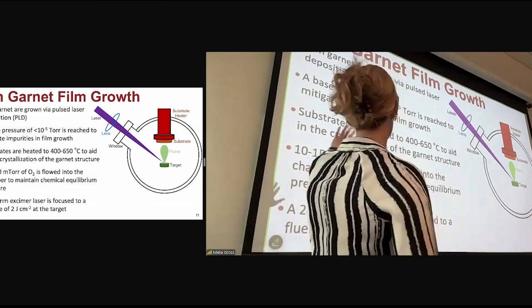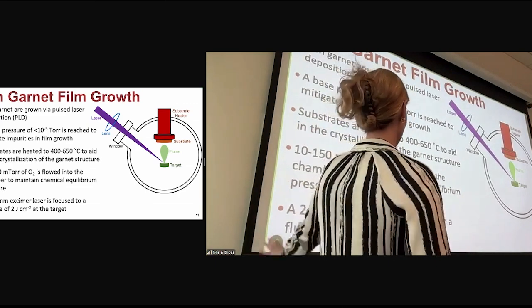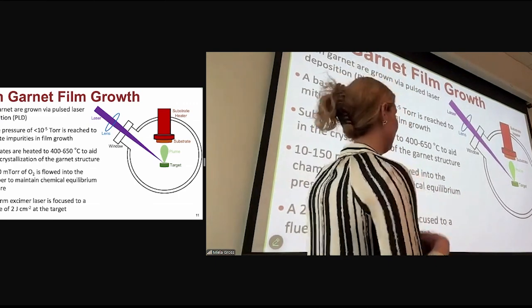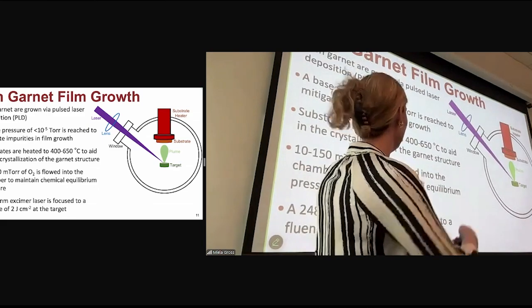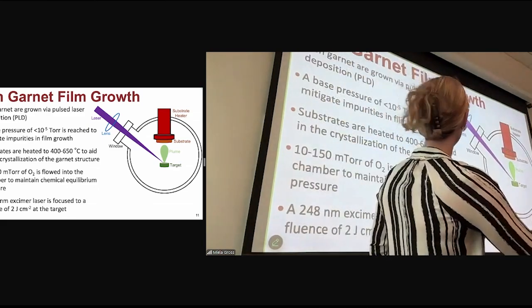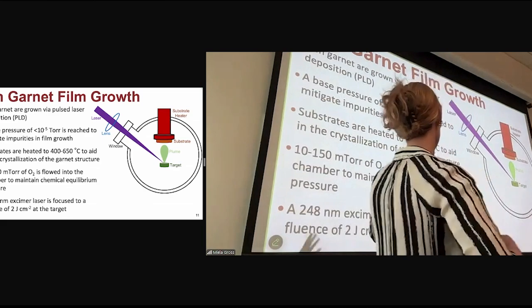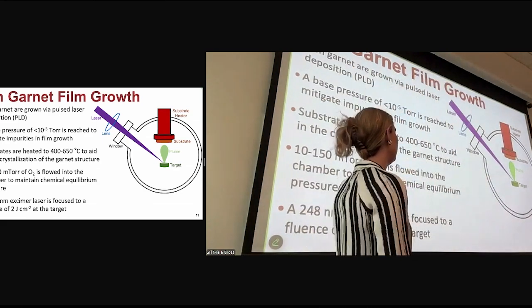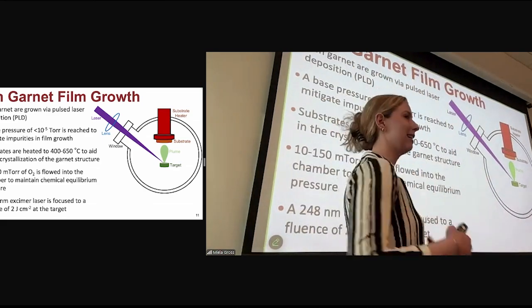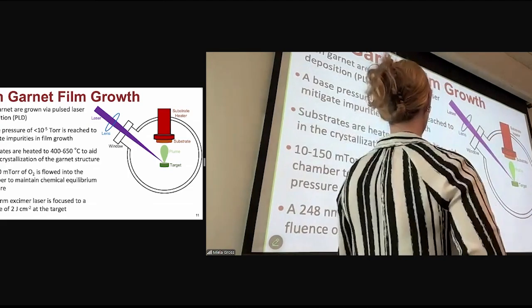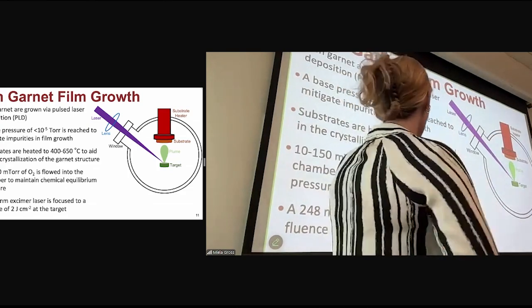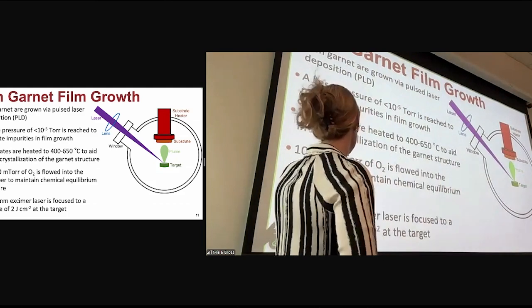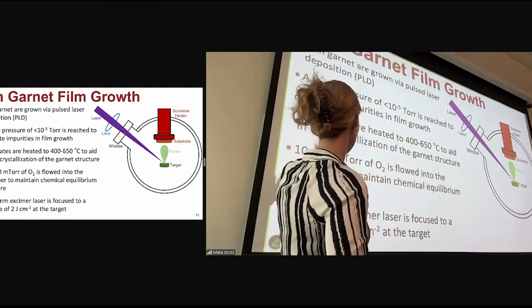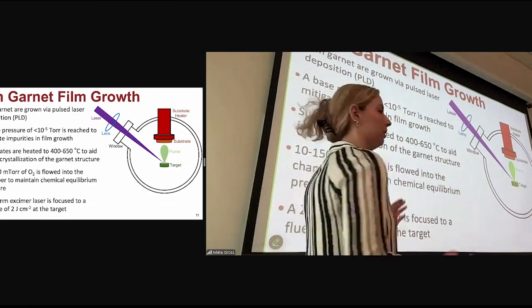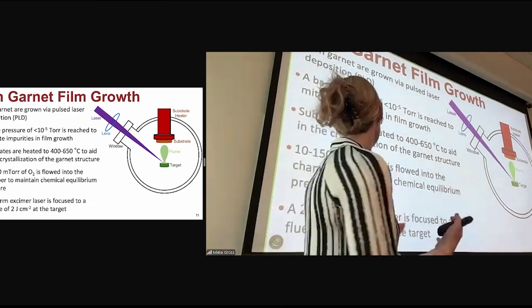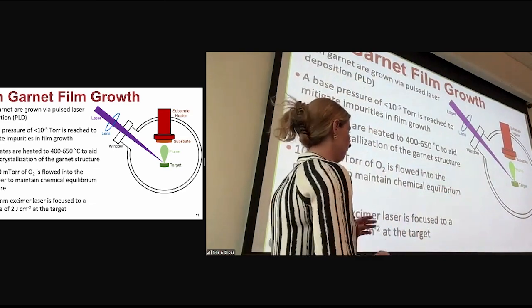So firstly, we can reach a base pressure of less than 10 to the minus 5 torr for our growths, and that mitigates impurities. Also, we have a substrate heater above our substrates, which allows us to heat the substrates to 400 to 650 C during our garnet growth. That adds extra kinetics to aid in the crystallization of the garnet structure. And we also are able to flow in oxygen while we grow these garnets, around 10 to 150 millitorr. And that actually helps us maintain chemical equilibrium pressure as we're depositing the garnet.